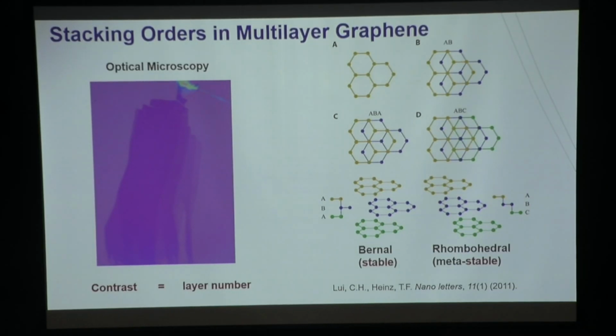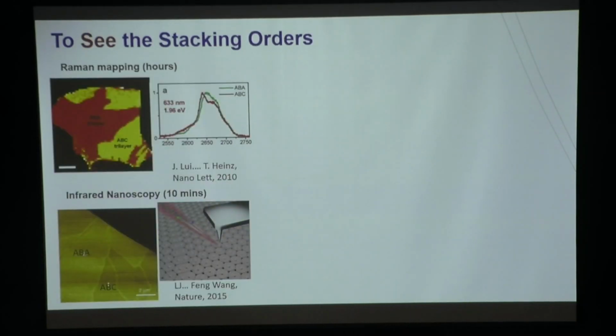And you don't have to believe me that there are these different configurations within a seemingly homogeneous region. There are really ways that allow you to visualize them. For example, you can look at the Raman spectroscopy spectrum of different parts of the flake. And if you look at the specific phonon peak, it's going to show different shapes, and that tells you where is the ABA, or the Bernal stacking, and where's ABC, which is rhombohedral stacking, right? You can do mapping by scanning your laser.